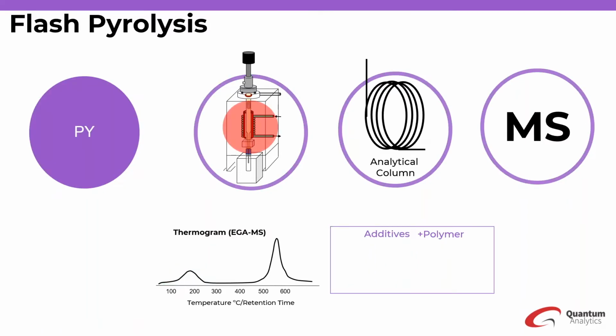In flash pyrolysis, the sample cup is dropped into a heated furnace and it's sampled isothermally. The result is a pyrogram of the various components in your polymer that was pyrolyzed at whatever temperature that you programmed it to. In this particular example, you have your additives and your polymer that's coming out at that particular pyrolysis temperature.